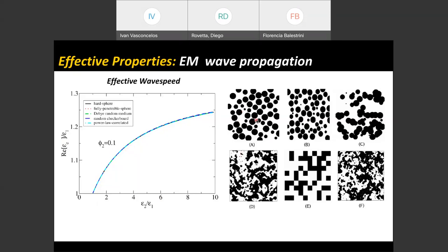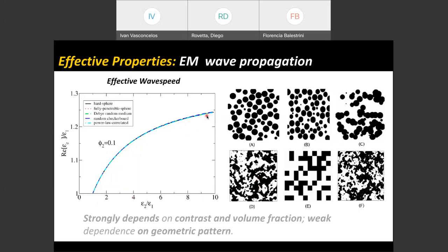So regardless of the material microstructure having very different geometries, the dependence of wave speed on contrast does not depend on the geometry of the material. This means that if we wanted to extract material geometry, say permeability, which is related to geometry, from wave speed, this is bad news because we can't tell the difference. In fact, we can say that effective wave speed, even though I'm not showing you different volume fractions, but we'll see this in a different example later on, strongly depends on contrast and volume fraction. In other words, it depends on the wave speeds themselves, and if this were porous, porosity, but it does not depend on the geometric pattern.